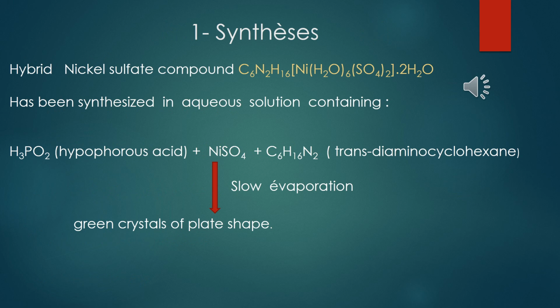Hybrid organic-inorganic nickel sulfate compound has been synthesized in aqueous solution containing hypophosphorus acid, nickel sulfate, and trans-diaminocyclohexane. Crystals suitable for X-ray analysis were obtained by slow evaporation.